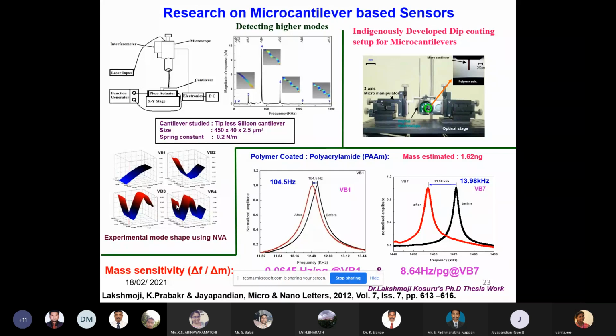Then with the same dimensions of cantilever used practically, and with a laser interferometric nano vibration analyzer, we monitored the frequency and recorded the mode pattern. That's what's shown in the bottom. Both are identical. It confirms that the simulation results and the experimental results are the same. It means the cantilever can go with the various modes of harmonics. Then going for a higher mode, is it possible to harvest high efficiency, likewise mass sensitivity able to attain.